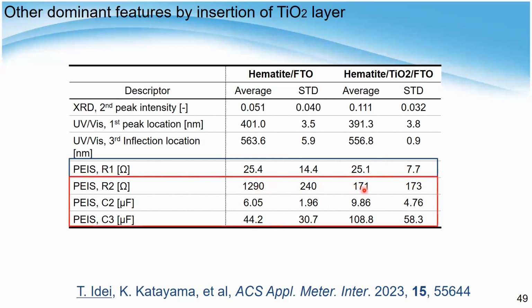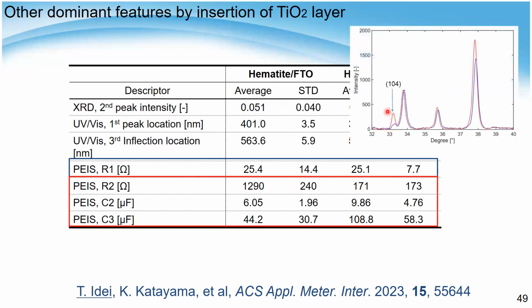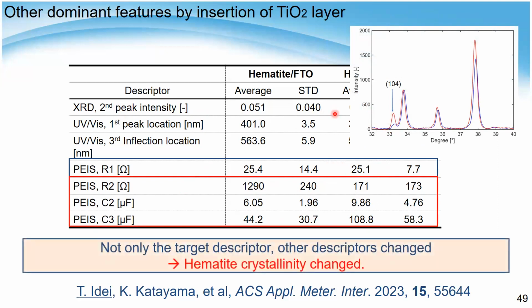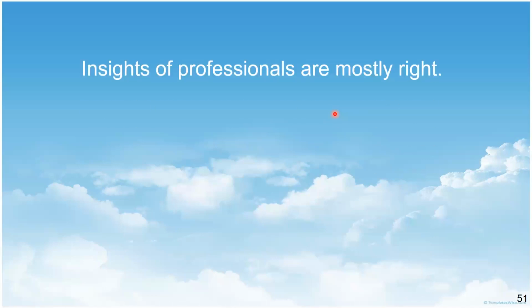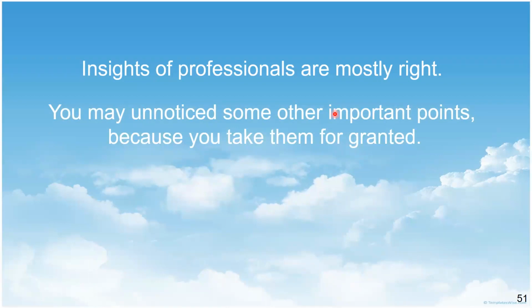But also some other parameters were improved, and we found that some of the XRD peaks were obviously enhanced by this. So not only the target descriptors, but other descriptors changed positively, right? And we could come to the conclusion that hematite crystallinity has been changed by this. So from this study, what we want to say is that people usually care about some specific part, especially professionals. Professionals already know which part is important and focus on it, but you may not notice some other important points, like this example, because you take them for granted. The machine learning function suggests some important improvements.